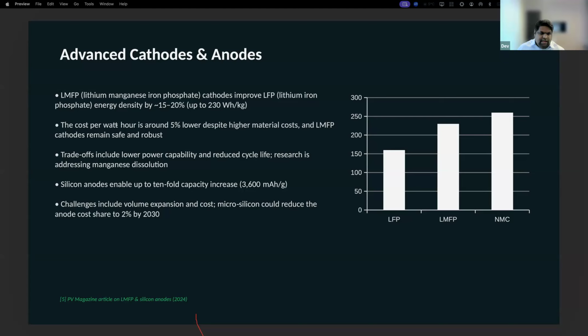On the anode side, silicon offers a theoretical capacity of 10 times that of graphite, which is currently being used: around 3,600 milliamp hour per gram versus 372 milliamp hour per gram. So this increases the density much higher compared to what is being used with graphite at the moment. Silicon, however, expands dramatically during lithiation, causing mechanical stress and capacity fading. During charging and discharging, a silicon anode would expand and contract, which puts mechanical stress on the battery cell.